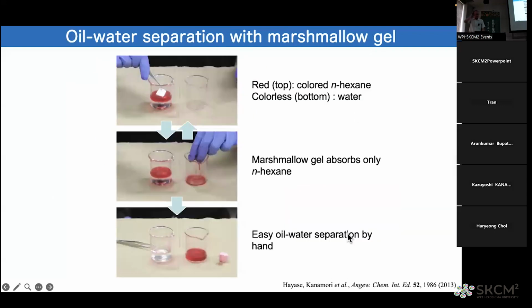So we showed that these materials can be used for oil-water separation because this aerogel, marshmallow gel, is completely hydrophobic. They don't absorb any water, so we can separate the oil, which is this red one, by a simple soaking and squeezing out process by hand. We can separate the oil and water very easily.